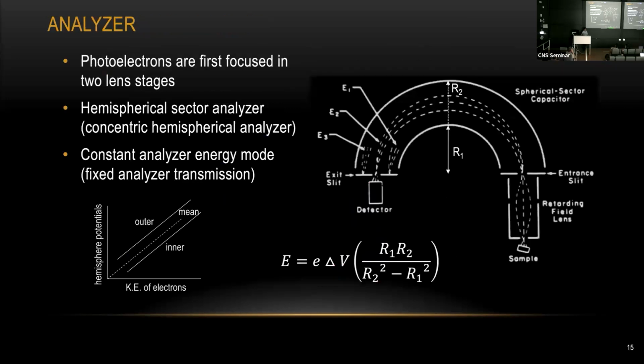And now the beam will be hitting your surface, and the signal will be coming out from your sample surface and go through the analyzer. The analyzer we are using in the lab is actually a 2-stage one. The first stage will be focusing your beam to the entrance stage here, so you are controlling the acceptance angle and maximizing the collection angle. And once you go through the second stage, your electron will be either accelerated or retarded depending on the energy.